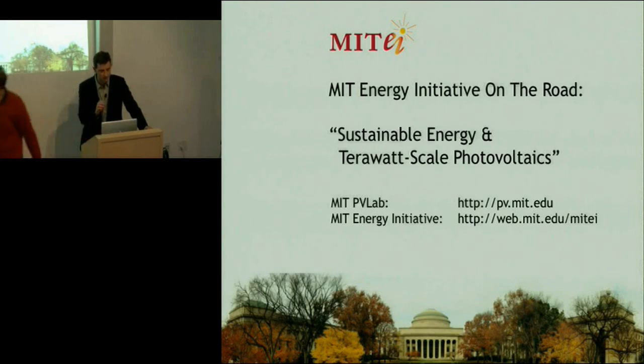And this particular type of material needs to be very well encapsulated to avoid any sort of degradation due to exposure to the elements or ingress of gases and moisture through the encapsulants to the active layer materials themselves. Because they're very, very thin layers, they're extremely sensitive to the ingress problems.